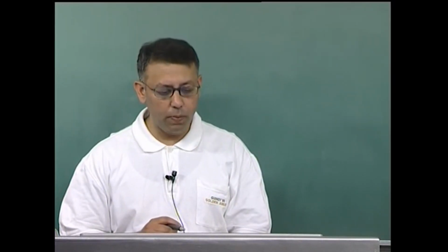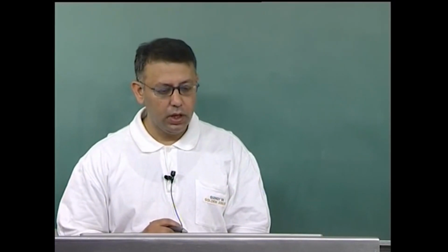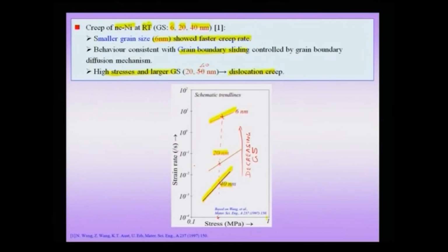So, we have all kinds of material here. We have pure palladium, pure copper, we have alloys like nickel phosphorus nanocrystalline material, and we also have nickel. And you see that each one of these, though some of them are very similar like nickel and copper are FCC materials, we do see a very wide variety of behavior in the nanoscale materials. So, as far as the understanding goes today, there is no generalized principle which we can apply to understand creep of nanomaterials, though we do understand some of the mechanisms which would be operative at larger grain sizes and the mechanisms which would be operative at smaller grain sizes.